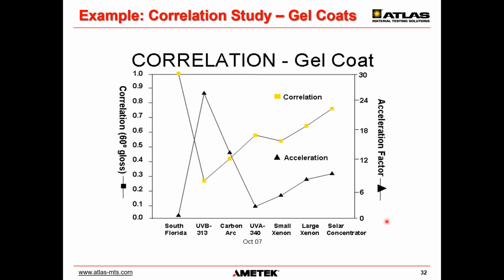So overall, and you probably saw the slide also in the acceleration presentation, based on these statistical methods, they found out that they can get a balance between acceleration and correlation by mostly realistically simulating the weathering effects. So realistic sunlight, realistic temperatures, controlled temperatures in artificial weathering gives the best correlation and also an acceptable acceleration. So the more realistic, the more likely it will correlate.